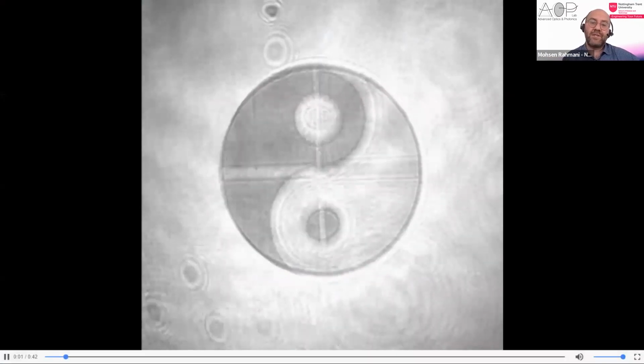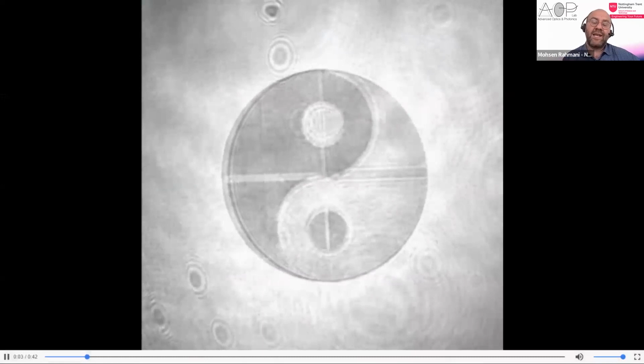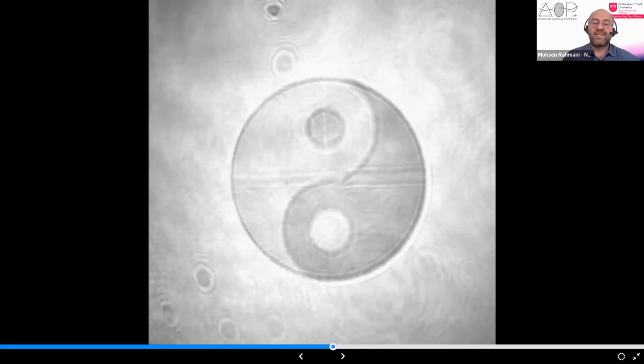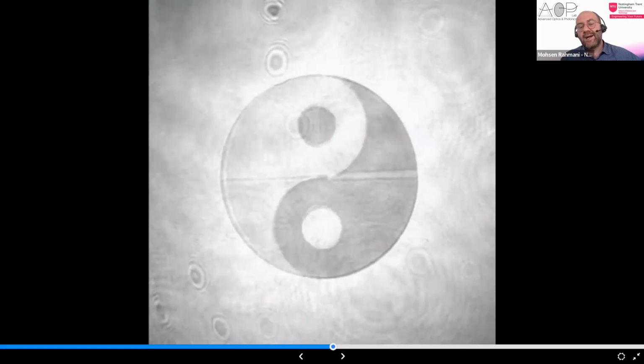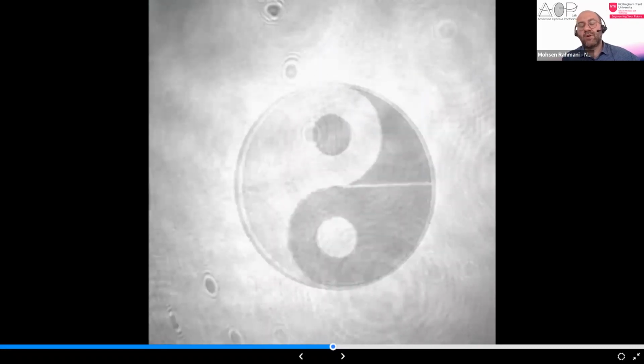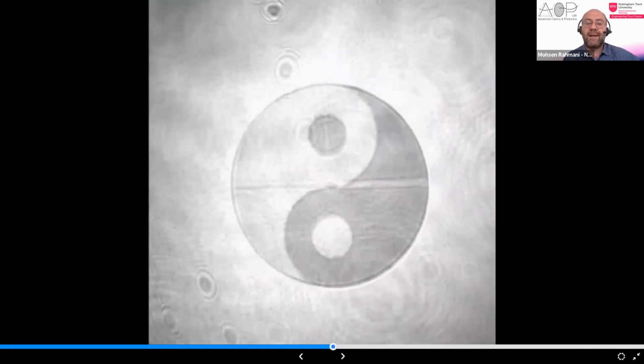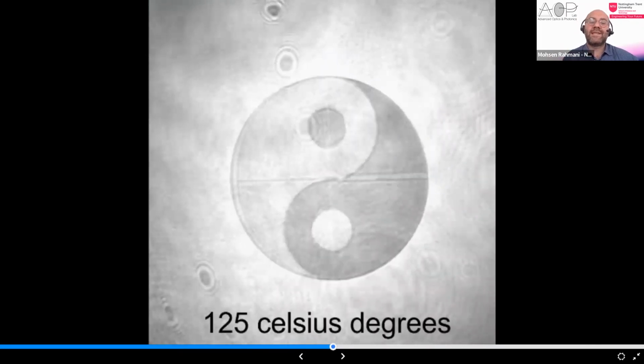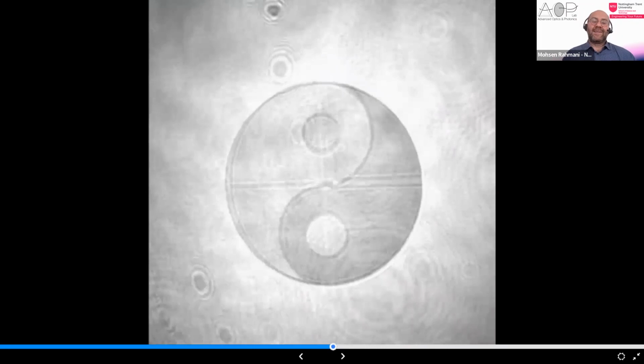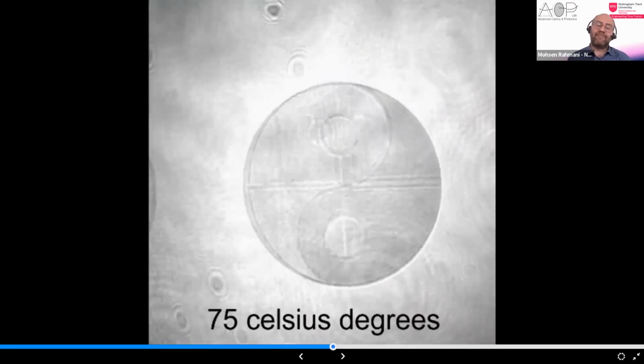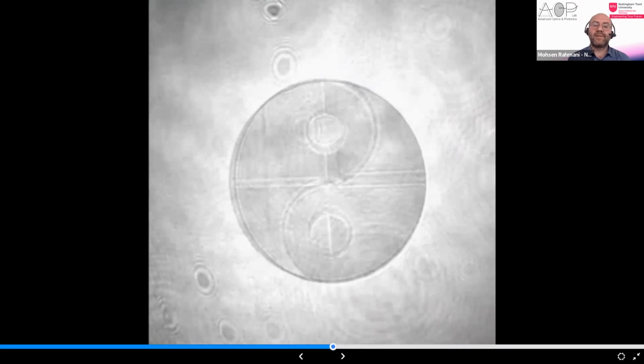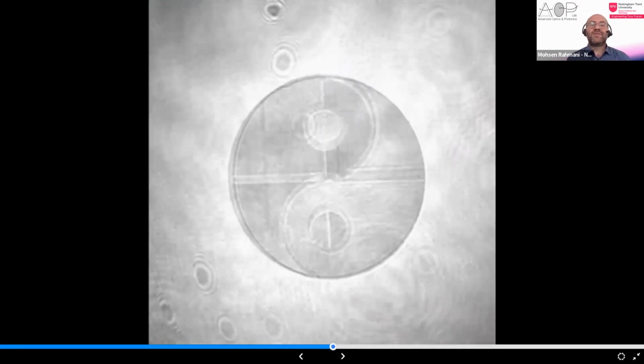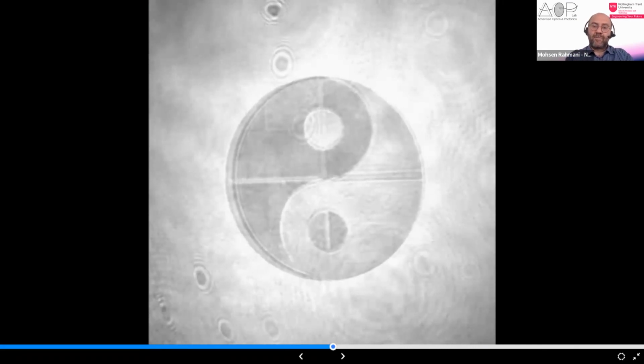In this video, if I can show you here, by increasing the temperature, you see that these areas on the left-hand side, which are opaque, become transmissive, and the other areas the opposite way. Then we are heating up the sample. After that, again, we cool down the sample, and you can see that it goes back to the first phase, and these samples can be used for ages. Nothing happens to that. It's very durable. And as you see, you can really and nicely control the contrast of this image.